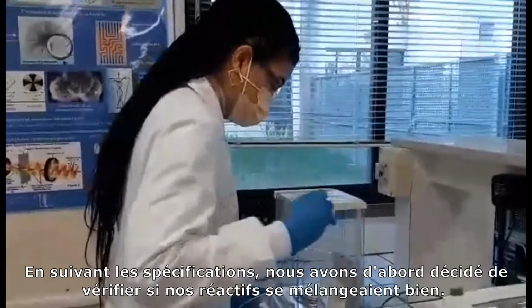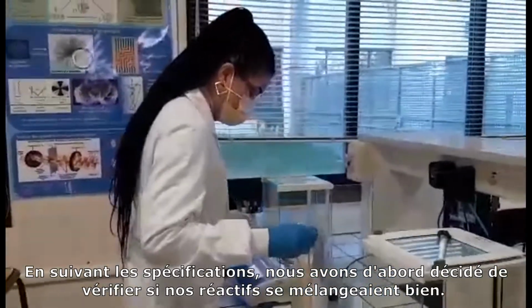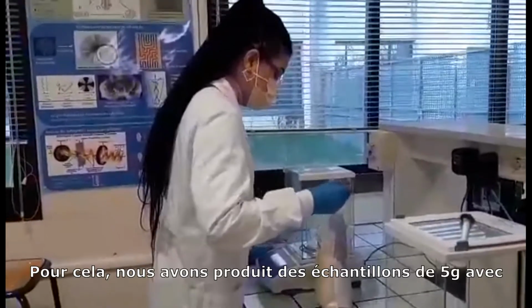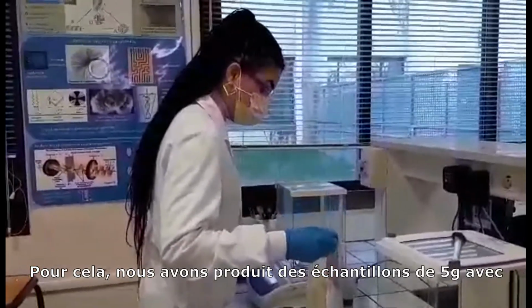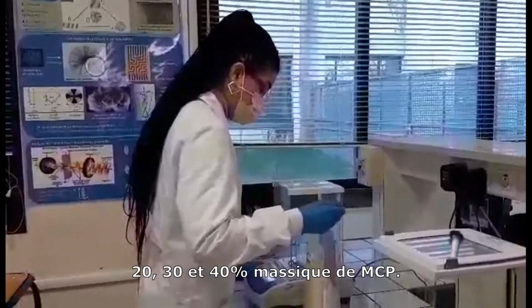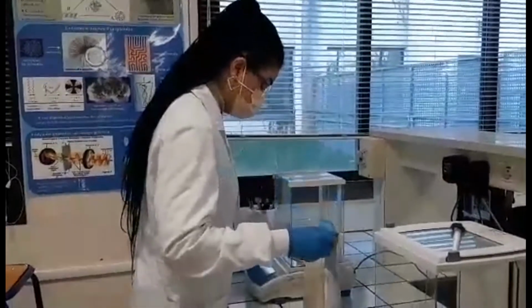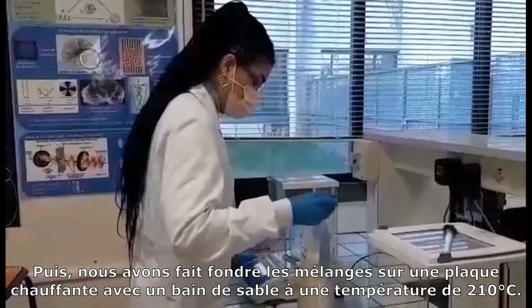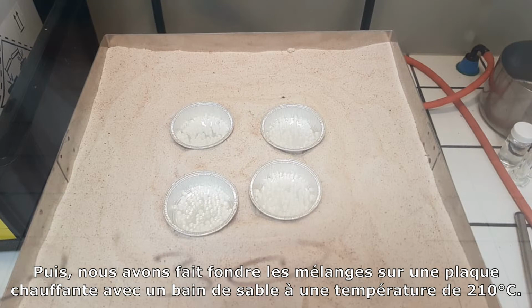Following the specifications, we first decided to check if our reagents were mixing well. For this, we produced samples of 5 grams with 20, 30 and 40% by weight of PCM. Then, we melted the mixtures on a heating plate with a sand bath at a temperature of 210 degrees.